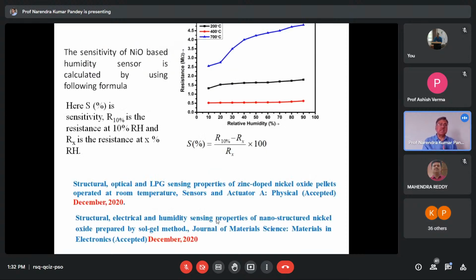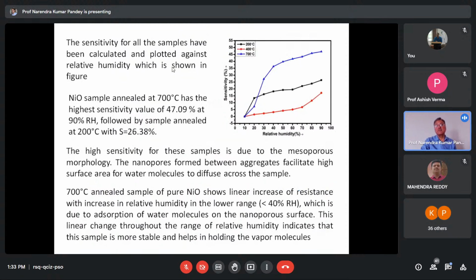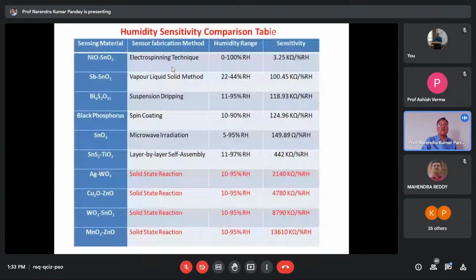And just for the case of it, I have shown a P-type material also. This has just been published in Sensors and Actuators. So the NiO-based humidity sensor, you can see from here. If it is N-type, because of the contribution of electrons, the resistance will decrease. And in the P-type, because of electrons being taken out from the surface, the resistance will increase. So if you are increasing the relative humidity, the resistance is increasing for P-type material like NiO crystal. And this is how it is, sensitivity versus relative humidity. And this is a comparison.